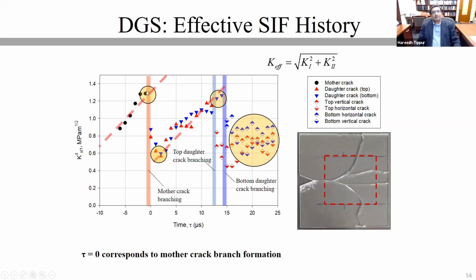And once the branching took place, the value once again dropped to a low value of 0.6, same value as in the smaller specimen. And this value again built up all the way to 1.2, 1.3 megapascal root meter and branched again. Once the branching took place, none of the granddaughter cracks show a value that is large enough.